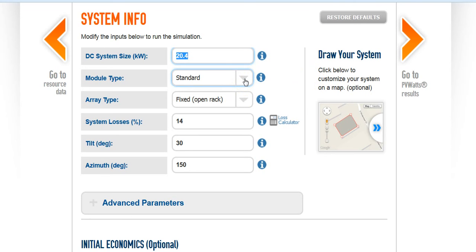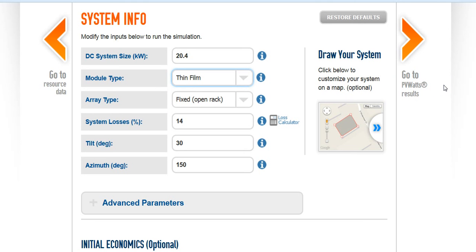Standard — what is this representing? This is the module that we're using. The standard module is a monocrystalline or polycrystalline silicon module; most of the time this is what you'll be using. The conversion efficiency that they're using here is 16%. The loss due to heat during the conversion of energy — they're calculating 11%. If we were to use a premium module, that would drop to about 8% to 8.5%. The premium modules that use layering or a tandem connection between a different technology such as amorphous silicon reduces the temperature coefficient, and of course we lose less energy due to heat with that factor. Thin films such as cadmium telluride — which is unlikely that you'll be using — has an even lower temperature coefficient, so they're factoring in about 5% to 6% net loss due to heat.